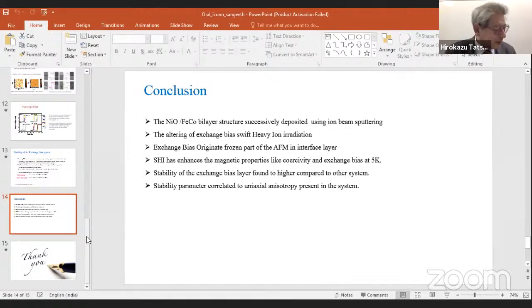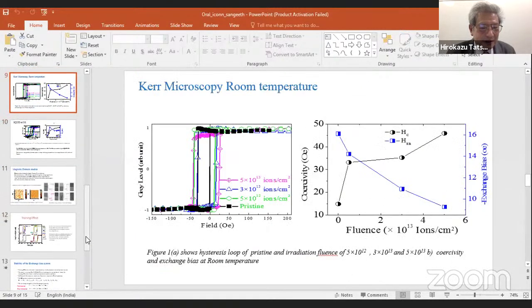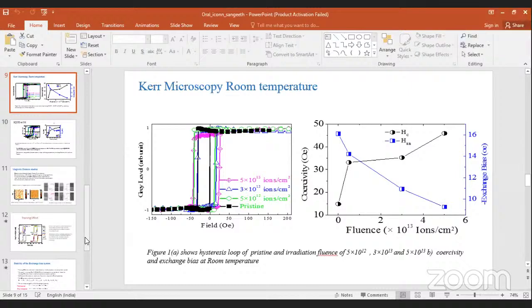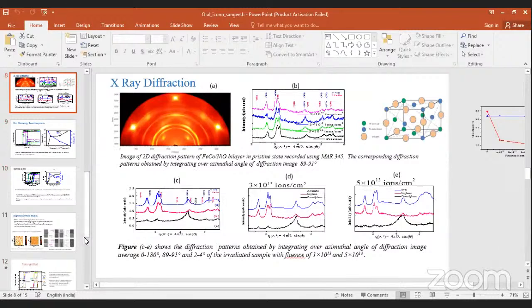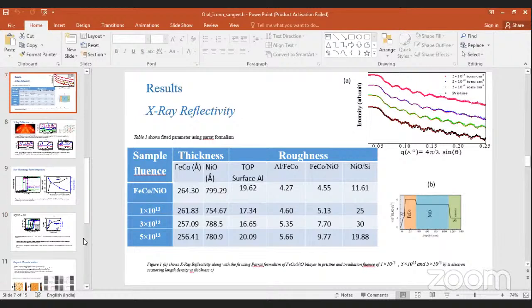So by the post-treatment, which characteristic is improved and which one is degraded? Actually, the stress induced in this film has been reduced, and stress relaxation has appeared. That's evidenced by the XRD pattern, and also the interface has been modified. It has become a rougher surface after the irradiation. When this roughness increases, the pinning centers at the interface create more exchange bias.